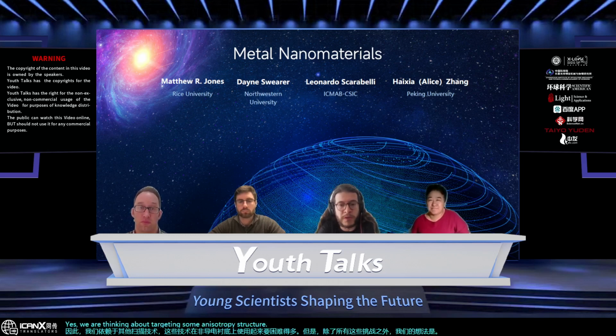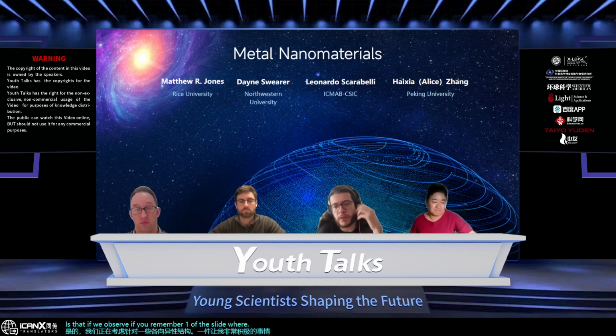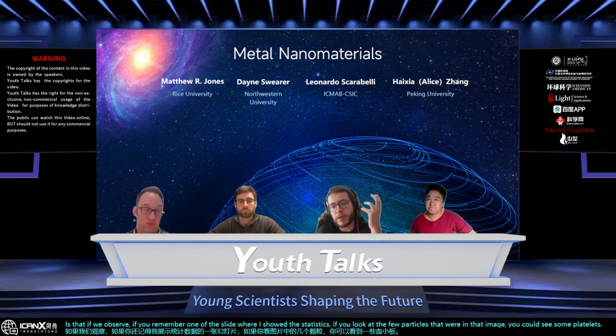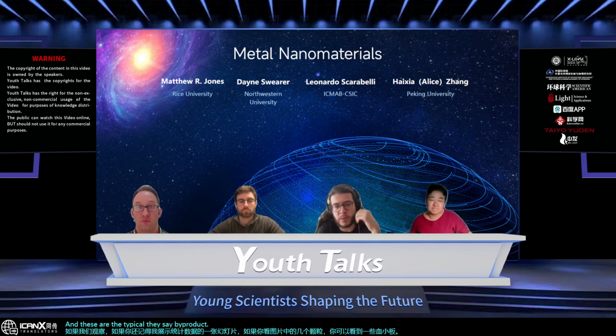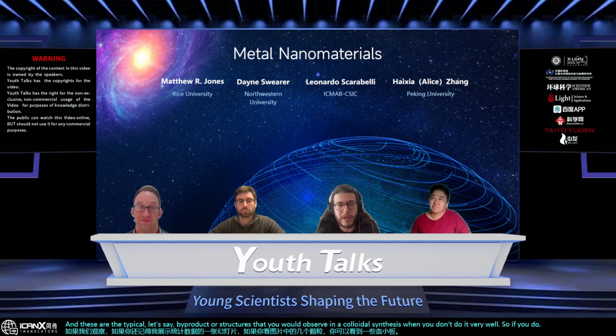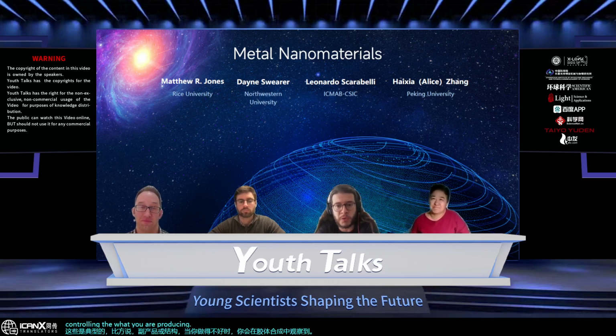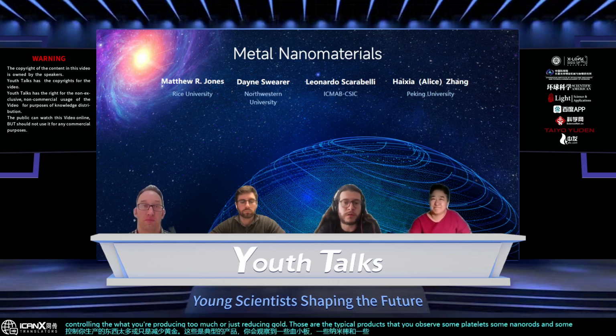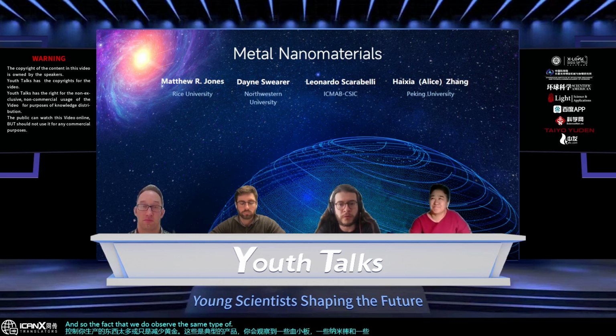But apart from all these challenges, yes, we are thinking about targeting some anisotropic structures. One thing that makes me very positive about it is that if you remember one of the slides where I showed the statistics, if you look at the few particles in that image, you could see some platelets and some nanorods. These are the typical byproducts that you would observe in a colloidal synthesis when you don't do it very well. So if you do a synthesis where you're not controlling what you're producing too much, or just reducing gold, those are the typical products that you observe: some platelets, some nanorods, and some decahedra. And so the fact that we do observe the same type of products tells me that at least to some extent what we know from colloidal synthesis will be translatable to this type of in situ growth system.